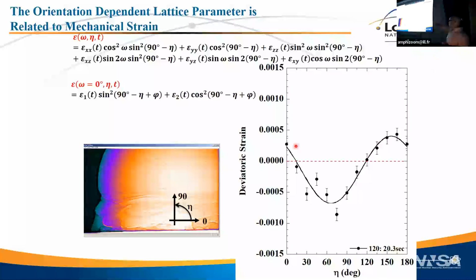evolution. So the waviness of this, that's the ellipticity of the Debye-Scherrer cone. So it starts out, this is at late time. So this is after it's cold. Sorry, I should point here. So this is after it's cold. This sinusoidal curve is the residual stress in the material. This is what it looked like when it first started. So this was the first measurement as a solid, and you see now that sinusoidal curve is gone. That's because it's hot and it's soft. It really can't hold a stress.